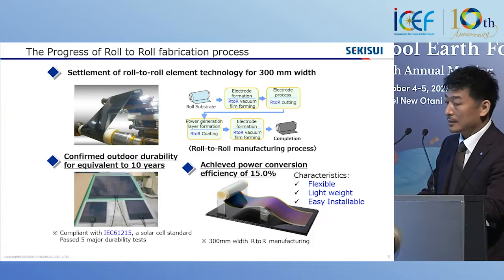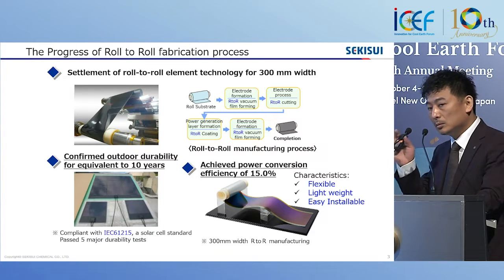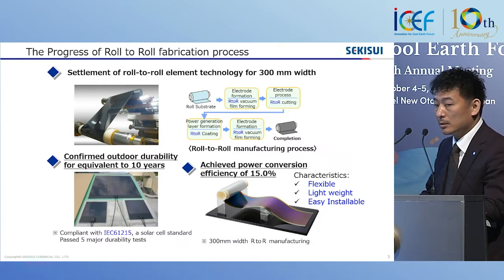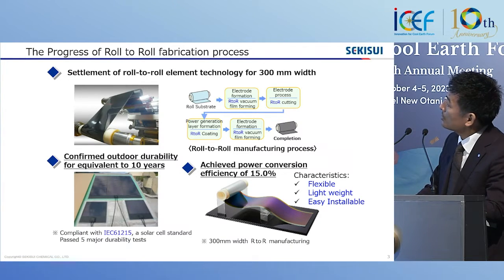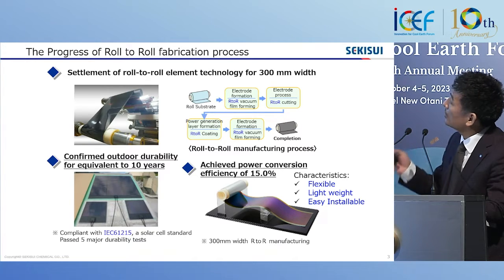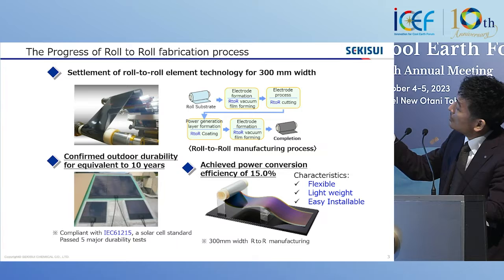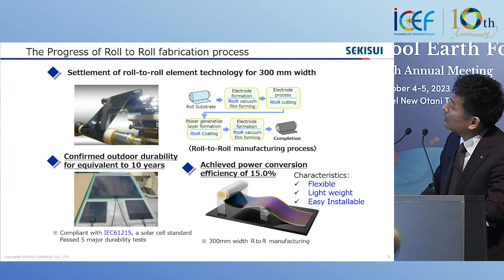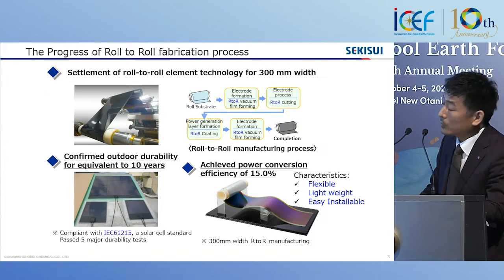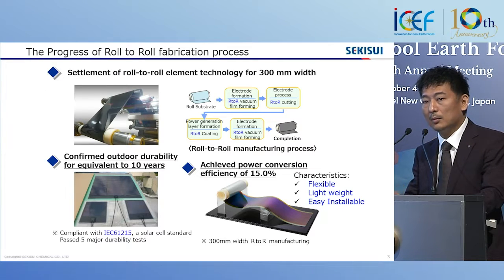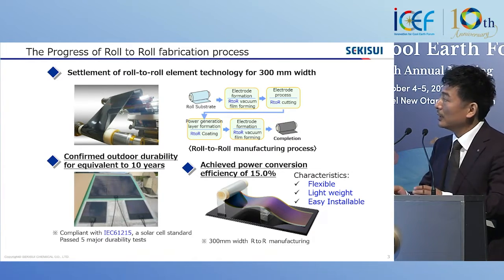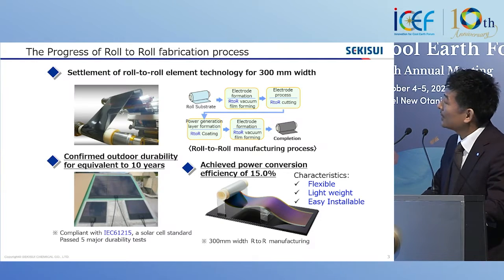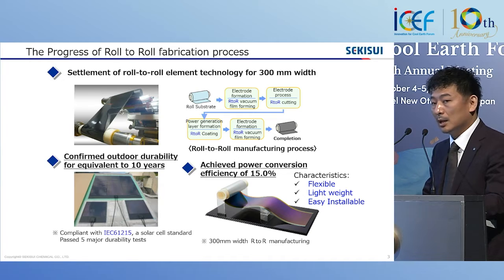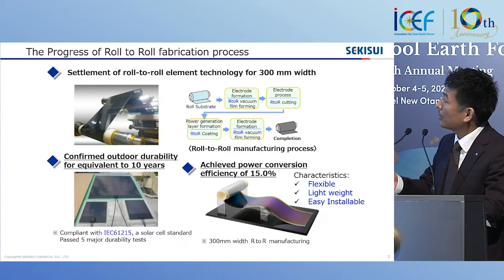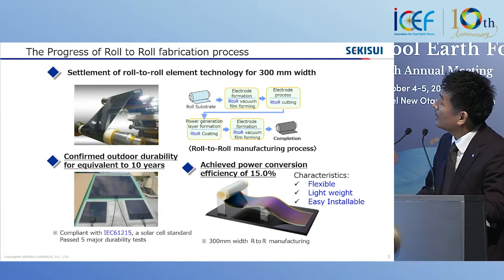In our systems, we are concentrated on the roll-to-roll system for the fabrication of perovskite devices. Now we are concentrated on establishing a 300 millimeter width. As you can see in the upper left-hand side, this is our roll-to-roll process, and the black part is the perovskite material. The roll-to-roll process is a very standard process in Sekisui Chemical, because we handle a lot of film. And then we have transferred the technology to the application of device fabrication of perovskite coating.